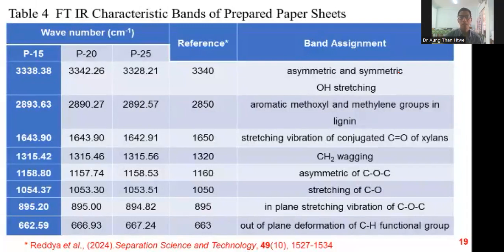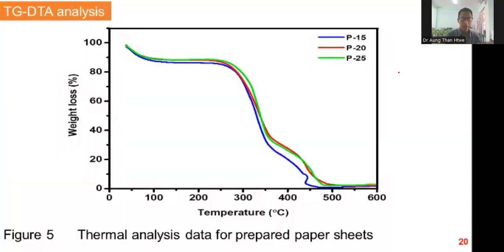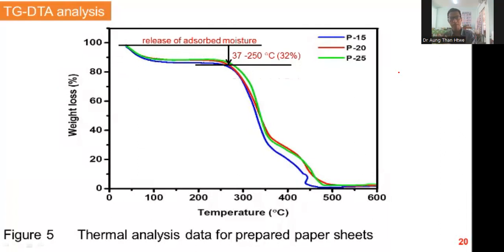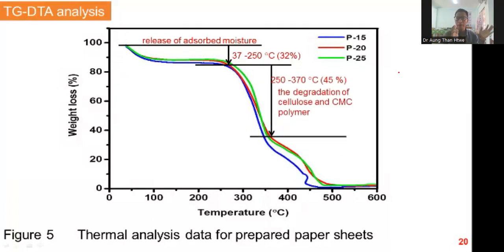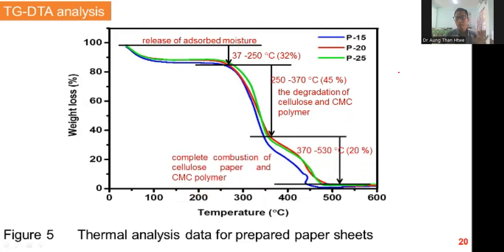This table shows every characteristic band of the prepared paper sheet. Now, let me continue with the TGA-DTA analysis. The thermal analysis data for the prepared paper sheet is as follows. The first stage is the temperature range 37 degrees Celsius to 250 degrees Celsius, in which all of the paper sheets show about 32% weight loss due to the release of some moisture. The second temperature range, 250 to 370 degrees Celsius, has a total weight loss of about 45%. This is due to the degradation of cellulose and CMC polymer. The third degradation temperature range, 370 to 530 degrees Celsius, has a total weight loss of about 20%.